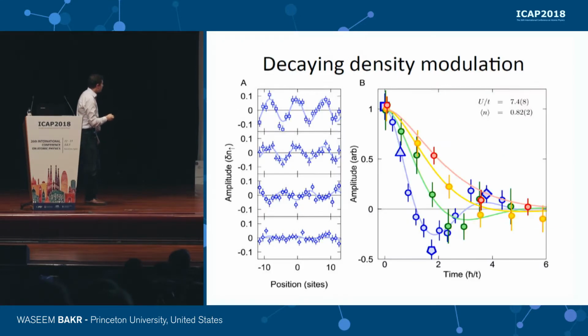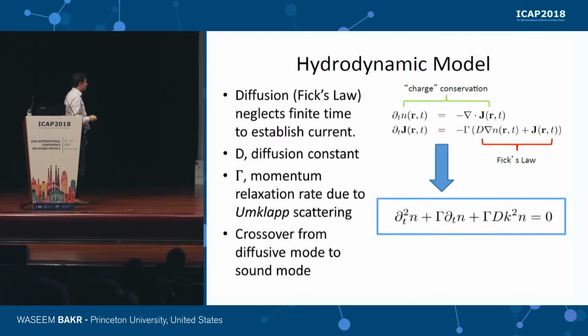Now, we clearly see that there are some inertial effects going on. We see this change in the sign of the amplitude. We see some curvature in the beginning. So that's not compatible with Fick's law. Fick's law tells you there's an instantaneous change in the current. So we kind of have to make the current change at some finite rate. So we introduce that the rate of change of the current reaches its equilibrium value in some time scale, which is the inverse of this gamma. So this we would call a current relaxation rate. OK, so there are 2 parameters here, the diffusion constant and the current relaxation rate.